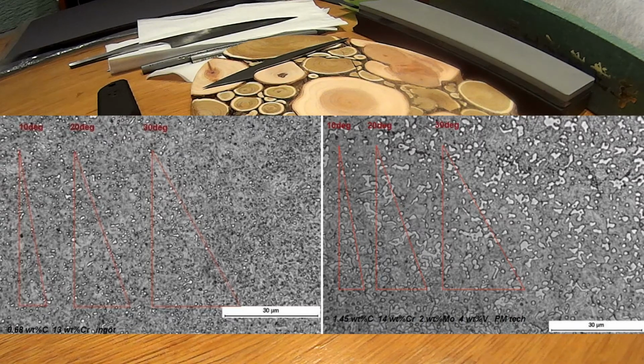Here you can see the size difference in particular between these two steels, and you can easily visualize how much matrix, or martensite, surrounding the carbides will be in the very apex of your sharpened edge. So the problem with high carbide steels is that the lower the angle you use, the less matrix is surrounding the carbides, and because there is no real bond between the carbides and matrix, once they're not surrounded sufficiently by matrix, that part of the material doesn't hold together and can be damaged by very light force.